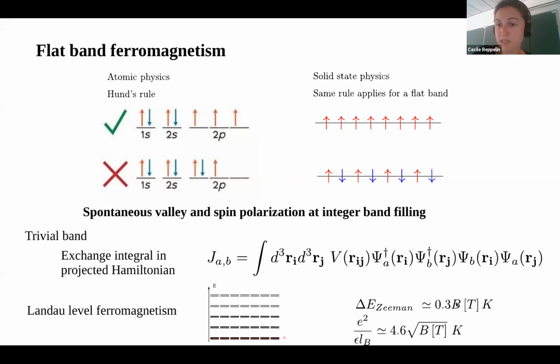So maybe around 0.3 times the magnetic field in Kelvin. Whereas if you consider the effect of exchange in this system, which is roughly of the order of magnitude of the Coulomb interaction, so that's why I'm calculating e squared over epsilon l_B here, it's going to be of order around 5 times square root of B, also in Kelvin. So for the magnetic fields that are accessible, this second exchange term is always much larger and is really what sets the value of the transport gap in the integer quantum Hall effect with an odd filling.